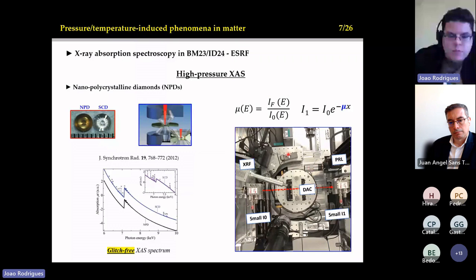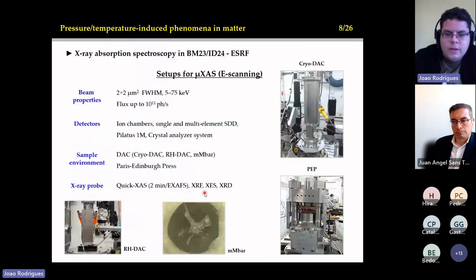And an additional thing is we need to use the nanopolycrystalline diamonds to have a good X-ray signal. The difference between the nanopolycrystalline diamond and the conventional one is that the nanopolycrystalline is a polycrystal. So it means that we don't have glitches that interfere with the X-ray signal. So this was a very important achievement in the community, to use this nanopolycrystalline diamond to really have a nice X-ray spectrum, and like this you can treat very nicely all the oscillations that you manage to have in your sample.